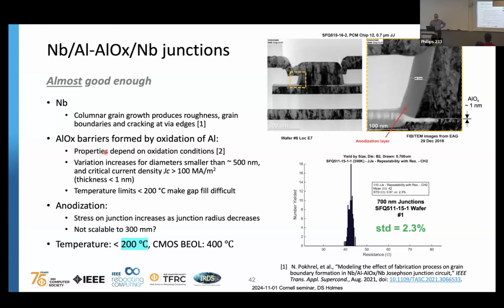It's amorphous, but it just got all kinds of things going on in it, and it's just not controllable. And if you get really thin, trying to make things thinner than 1 nanometer controllably is tough. And the temperature limits for the niobium and the aluminum oxide, it's less than 200 degrees Celsius. So that makes any other processing, you gotta figure out low temperature processes. And that's a pain, costs money, takes time.